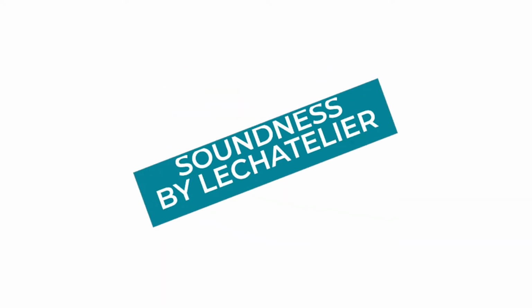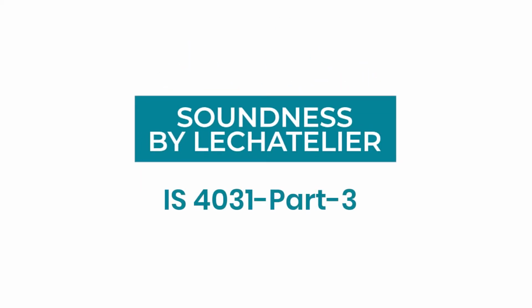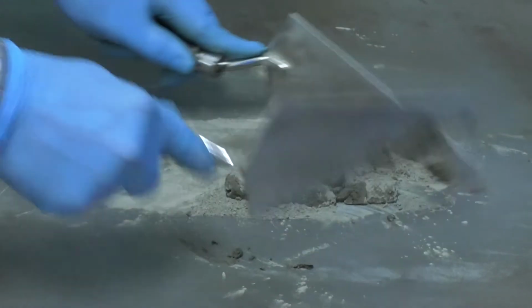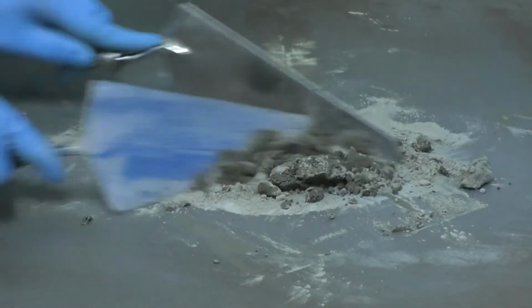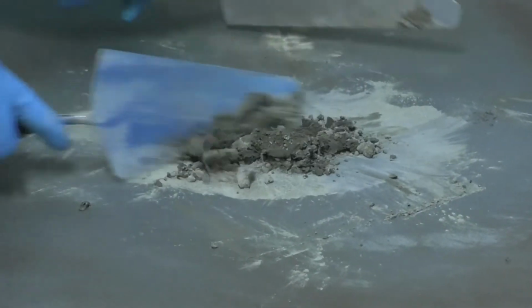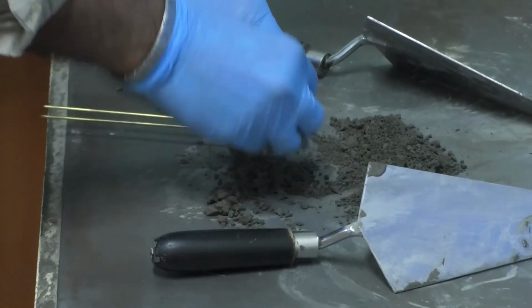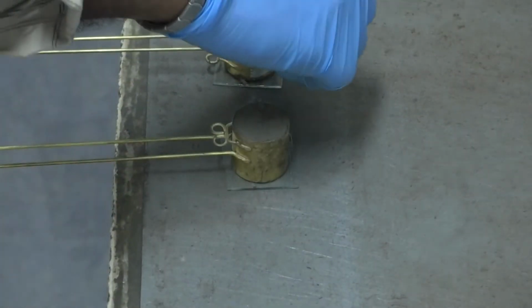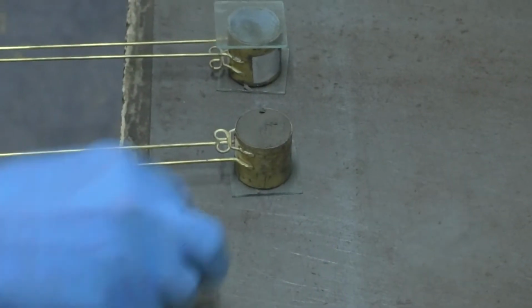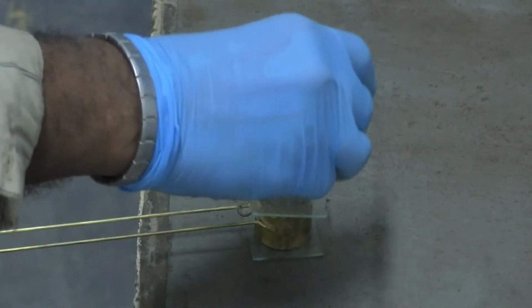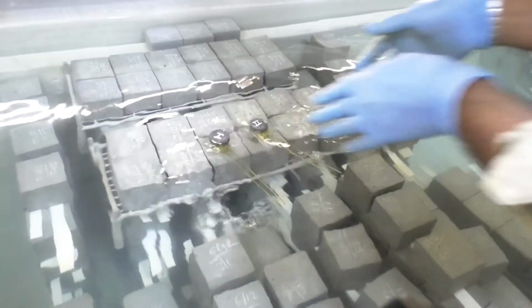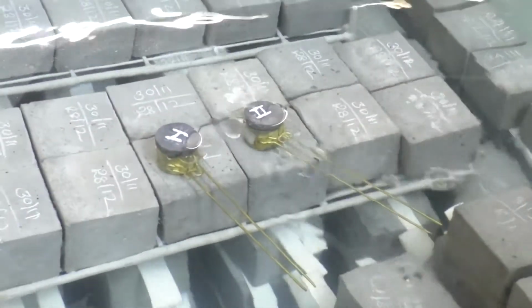Soundness by Le Chatelier. This test is performed as per IS 4031 Part 3. Prepare cement paste using water 0.78 times of consistency. Place the mold on a glass sheet. Fill with cement paste, cover with another glass sheet and place a small weight on the covering glass.